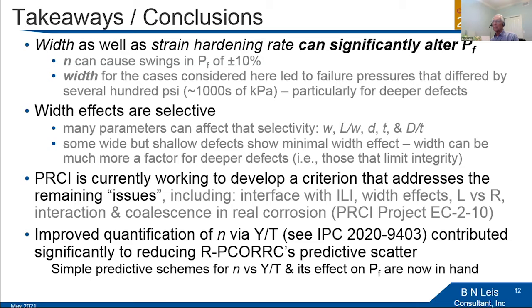takeaways and conclusions. As I've discussed very quickly, width as well as strain hardening rate can significantly affect the failure pressure. And it can be a reduction, and that's the critical part of it. Reduced failure pressures as compared to what you predict are very bad news. The strain hardening exponent can cause swings in failure pressure to the order of 10% or more. Width can cause swings in failure pressure of several hundred PSI, not trivial.